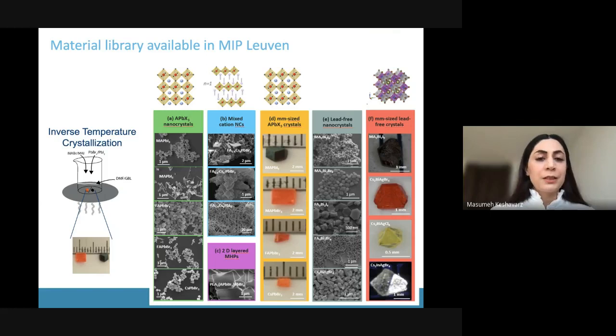Following the recipe, actually. So depending on the ingredients and also the solvent and the procedure where you make the material, we could achieve the lead-based perovskites from nanometer scale to millimeter single crystals, as you can see here. Also, we could have wires, cubes, and even the layered perovskites with the 1 layer, 2 layer, and 3 layers, tuning the number of the layers, as well as lead-free perovskites and double perovskites, which I will talk about at the end of my talk.